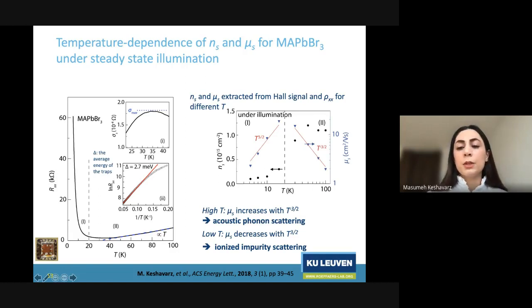However, from the temperature dependence of the mobility, we can actually identify the scattering mechanism in the system. So we see that in regime 1, the mobility scales with temperature with a power law of 3/2, and this is an indication of ionized impurity scattering. When we increase the temperature further, which is regime 2, we see that the mobility scales with temperature with a power law of -3/2, and that is an indication of acoustic phonon scattering being the dominant scattering mechanism in the system.